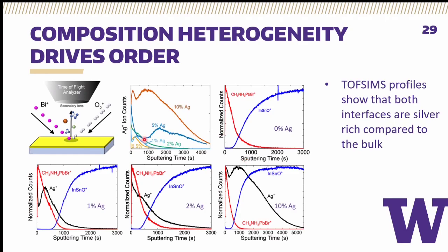So to probe the elemental composition through the depth of our film, we took these TOF SIMS profiles. We performed a time of flight secondary ion mass spectrometry measurement on each of our thin films, with the idea being you have this elemental sputtering probe that generates these secondary ions that are taken to a time of flight analyzer, analyzed by mass, and then we can compare the fragments that come off at different depths through our film to characterize exactly what's happening. We did these on ITO substrates in order to minimize the amount of charging in our sample and also to protect our perovskite from silicon, because there are silicon bromide fragments with the same molar mass as our silver.